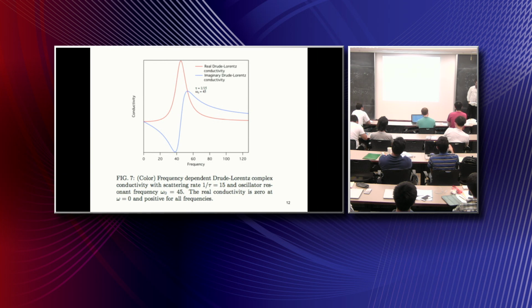So what it means is, in terms of modeling spectra, it's wonderful if one has a real model where you can model spectra and look at something with it. But in terms of emulating spectra, you can always do it, depending upon how accurately you want to, with enough finite frequency oscillators. If I have some experiment where I measure the optical conductivity, I can emulate it with, let's say, 1,000 different finite frequency oscillators, and the Kramers-Kronig relations, because they're linear, automatically output the correct imaginary part of the conductivity. Okay? And so this kind of fitting routine is used for the analysis of optical conductivity data all the time.